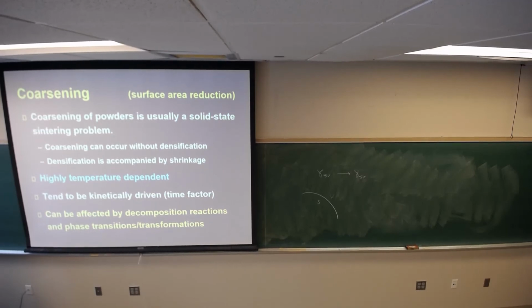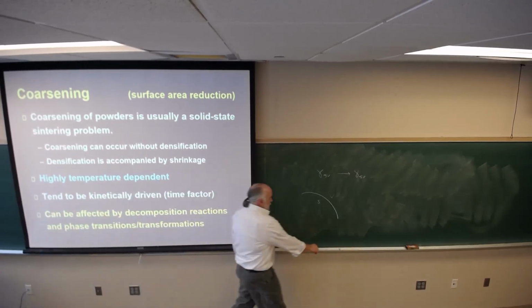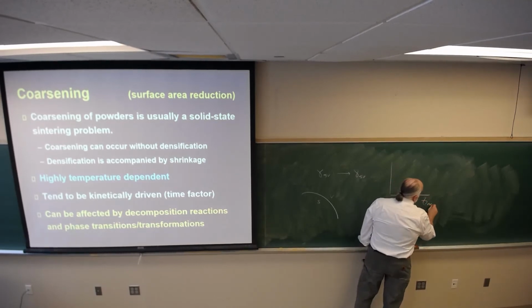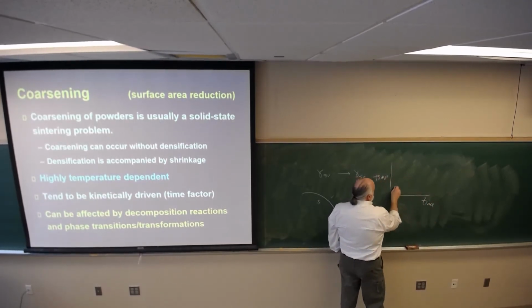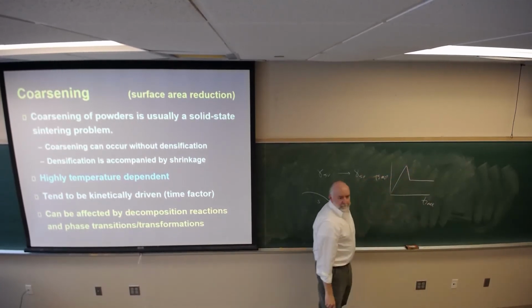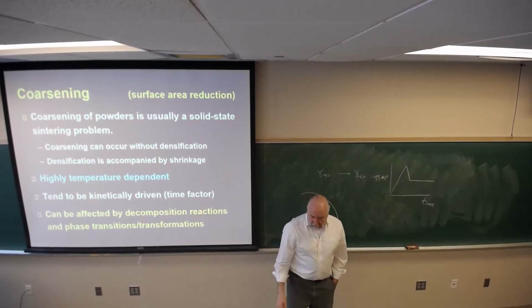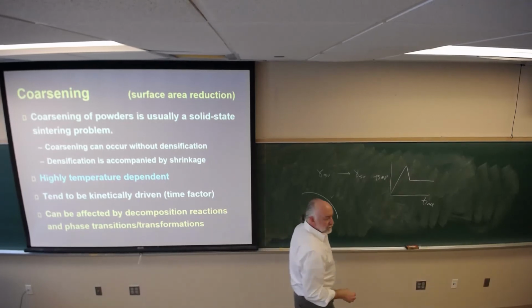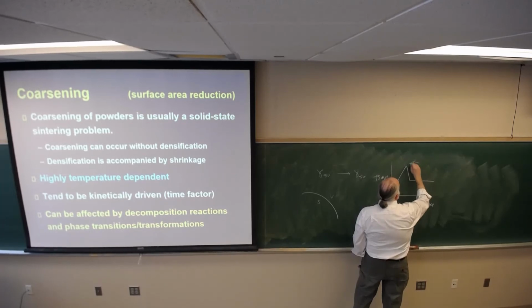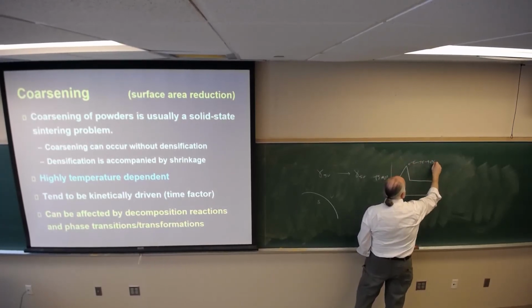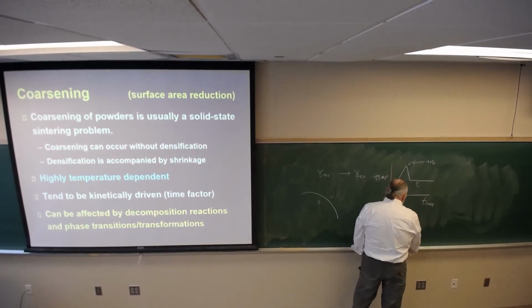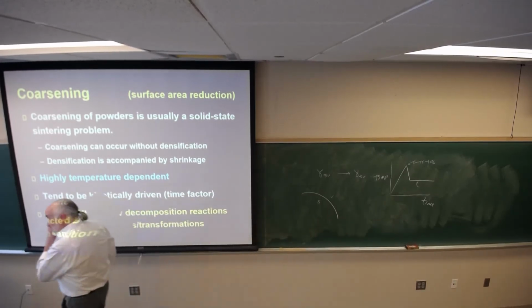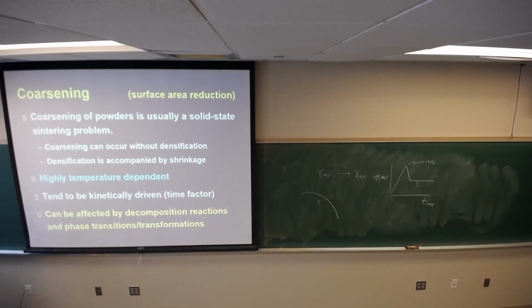So we are really interested in this phenomena right now for a concept called two-step sintering. And I will only touch on it. I don't have any slides yet because we're still generating data. What you do is you actually have a very interesting sintering curve. It looks like this. Time, temperature. You go up, you spike, you come down, you hold. Okay, and you actually dramatically reduce the grain growth potential in the system. You get full densification. This density at this point is 75 to 90% dense. Okay, and then here, this temperature might be very low. For alumina, typically we sinter around 1550 to 1600, 1500 to 1600. You might be doing this second stage someplace around 1150 or 1200.